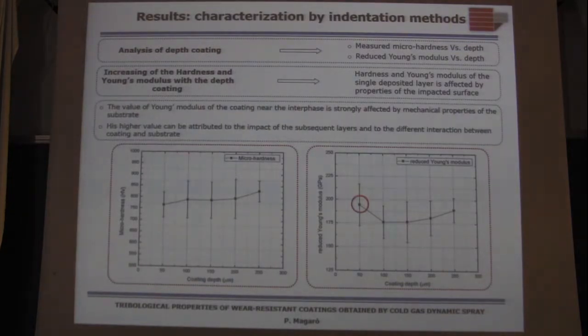But the value of the Young's modulus of the coating near the interface between substrate and the first layers of coating is strongly affected by the mechanical properties of the steel substrate. And this higher value can be attributed to the impact of the subsequent layers and to the different interaction between the first layer of coating and the substrate.